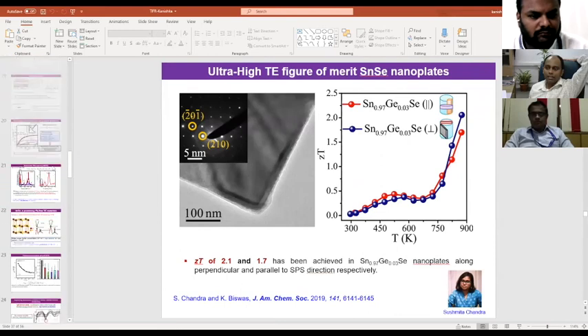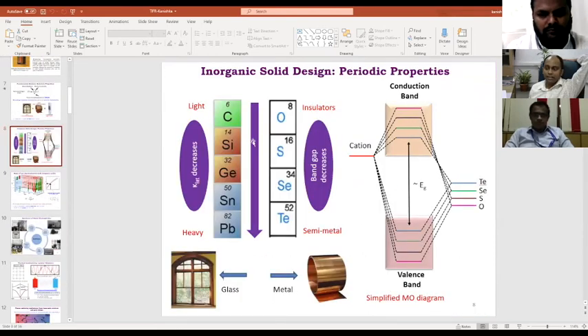But if you remember the diagram I presented, what I mean is that oxides have a very, very high band gap, so the conductivity may not match the tellurides. At the same time, these oxides are low mass, so you start with very high thermal conductivity. Both properties do not converge in oxides. You start with 20 watt per meter Kelvin, while a base oxide has a thermal conductivity of about 3 to 5 watt per meter Kelvin, but we are talking in terms of 0.3, 0.4. So that is the drawback of oxides. If you get a very high ZT in an oxide, that would be a real breakthrough in this field. But the thermal conductivity looks extremely high, so it may not be feasible.